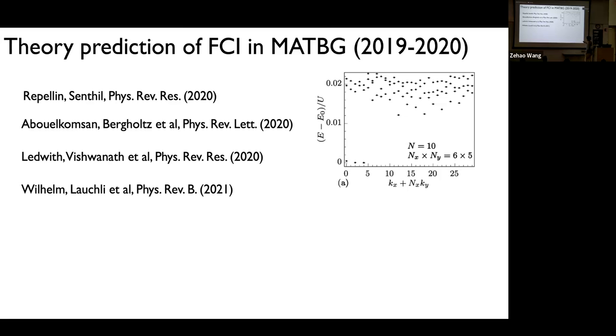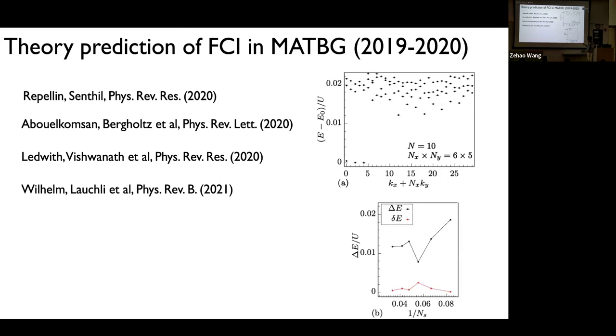What you see here is that there are exactly 3 states that are separated by an energy gap. And I think they also looked at the entanglement spectrum, and it's really a 1/3 fractional Laughlin state. In addition, they also looked at how robust this energy gap is, because at the end of the day, if you want to detect this, what matters is the energy gap. And it looks like the energy gap is not too sensitive to the model parameter.